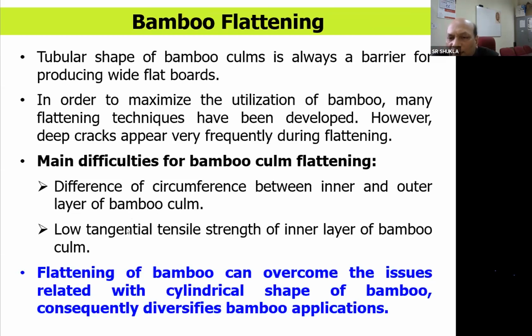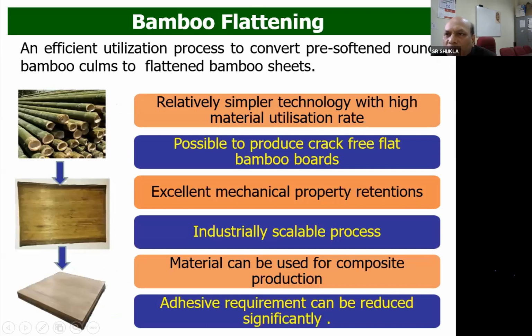So this makes the flattening slightly difficult, but when we treat the bamboo at a certain temperature using steam, it becomes flexible, and by using a roller it can be done easily. So flattening of bamboo can overcome the issues related to the cylindrical shape of bamboo, consequently diversifies the applications of bamboo. This is the process by which bamboo flattening is taking place. Relatively simple technology with high material utilization rate, and it is possible to produce crack-free flat bamboo surface boards. Excellent mechanical property retention, industrially scalable process, and the material can be used for composite production, as I told. And then the adhesive requirement can be reduced.